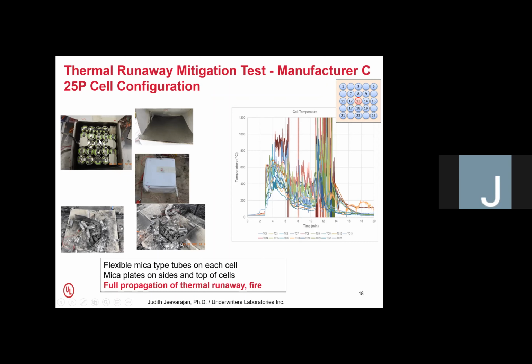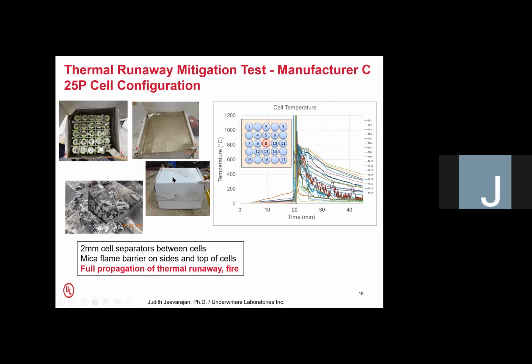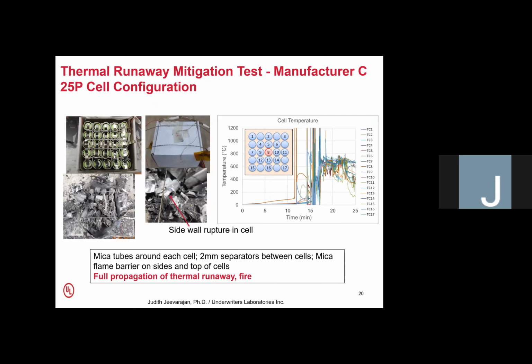But in this case, we used the mica plates and the cell sleeves, and we found that we had complete thermal runaway. In this particular case, we used the intercell separators and the mica blanket. Again, as you can see from the picture, we had a complete thermal runaway. And in the last case, we used the cell sleeve, the intercell separators, and also the mica plates on top and the bottom, and the flame barrier sheets on the top and the bottom, and also on the sides.